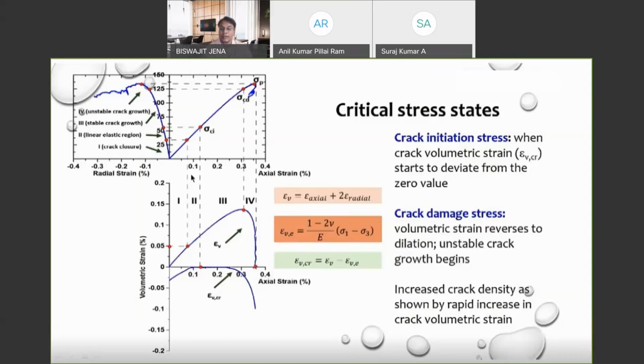So if I take the point of volumetric strain of 0.05 and come to the volumetric strain curve, and then go hit the curve on the elastic part, then that pretty much is the first part, that is about 25 megapascal or around that range where you are actually compressing. So you are getting that increased stress because you are closing all the micro cracks within the specimen. So you have the small positive volumetric strain, but you are closing micro cracks in that specimen.